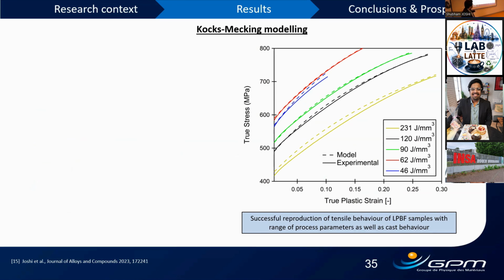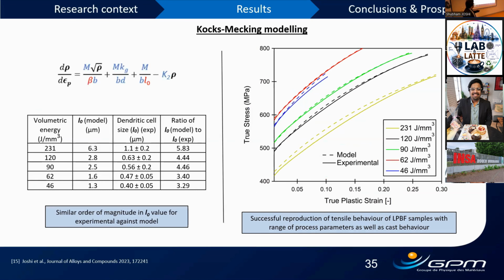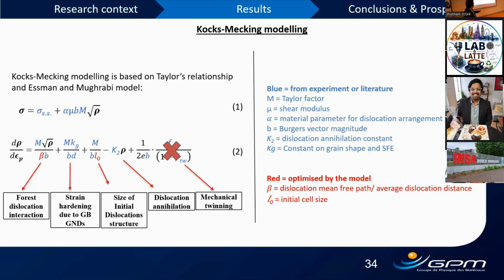So, true stress versus true plastic strain. Using the model, actually, there was one thing I could also tell you: in this model, if you can see all the blue parameters, they have been directly taken from the experimental literature, but only two parameters, beta and L0, have been optimized by the model. Now, you can see that L0 we already have. This is the average cell size, but we decided to model it so that we can see if our model works, if we get modeled values somewhat similar to our experiment.